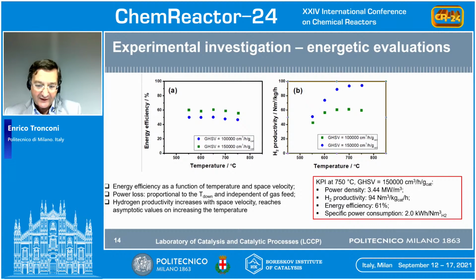We did some calculations to evaluate the energetic performances of our system. And we found that the highest energy efficiency was something like 60%, corresponding to a very low power consumption per unit hydrogen production, limited to about 2 kilowatt-hour per normal cubic meter of hydrogen, which is markedly lower than the specific power consumption typically reported for industrial electrolyzers.